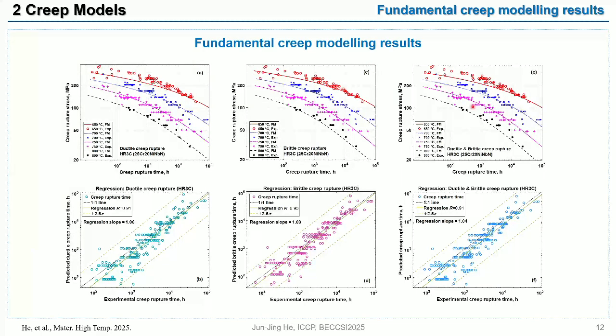Now here, the three figures above show the predictions from the fundamental creep models. The data points here are experimental data from different sources, and the lines are the prediction results with the ductile creep rupture models, the brittle models, and also a combination of both. The three figures below show the corresponding regression analysis for the predicted creep rupture time versus the experimental creep rupture time. In general, there are no significant differences between the statistical analyses for the three ways. Both the regression coefficient and the regression slope are quite similar. But we can identify that, for example, at lower stress and higher temperature levels, the brittle creep rupture dominates.